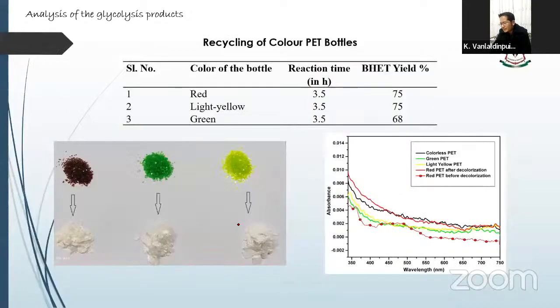And we also carried out the effect of added colors on the catalyst efficacy. And we carried out these depolymerizations of different PET color bottles. And as you can see, all the reactions were completed within 3.5 hours of reaction time. And most of the color separates out during the crystallization process.